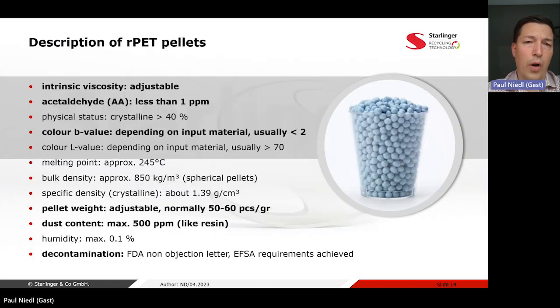Typically, the quality that you expect from recycled PET to go back into a preform has to be absolutely comparable with virgin material. So the magical numbers here are acetaldehyde, maximum 1 ppm, 40% crystallinity, color values, L value typically around 70, B value between -2 and +2. And of course, IV is adjustable, pellet weight is adjustable depending on the requirement that your customers have.